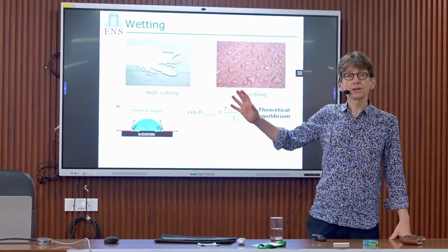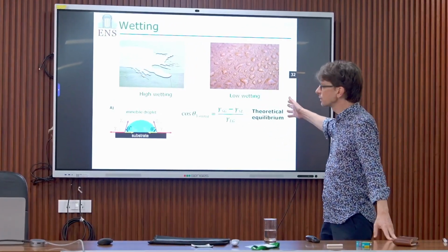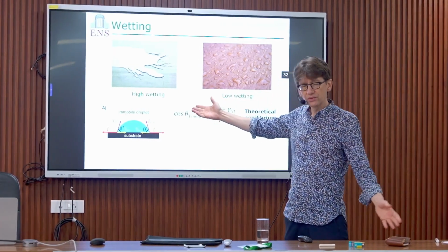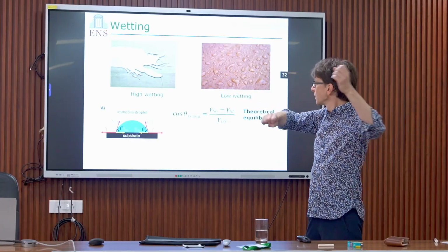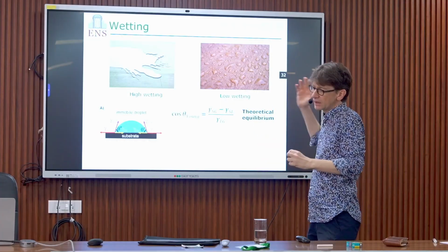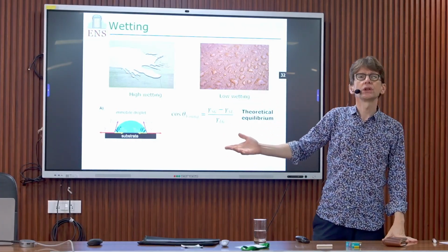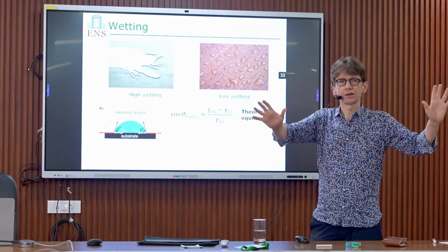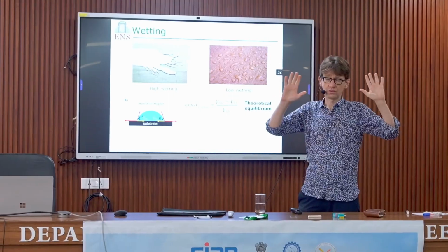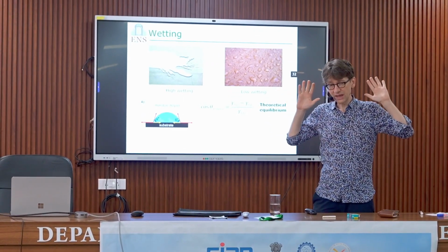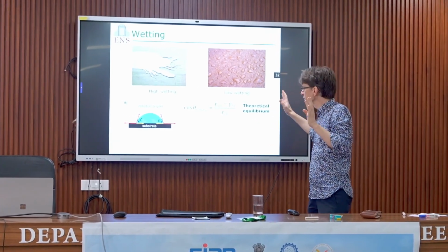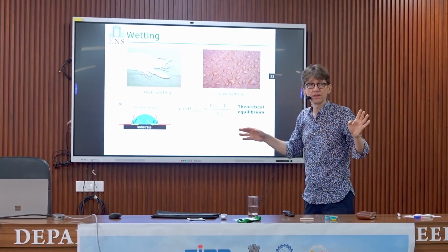The thing is that, of course, in this representation, you don't have to remember this equation because it's very easy to find. You can find it on the internet or whatever. But what you need to remember is that in this cos theta that we write by the Young equation or whatever, there are no other forces than interfacial energy. This is what you need to remember. As soon as you have additional forces, there will be something else. You cannot just use this equation as long as you have other forces.